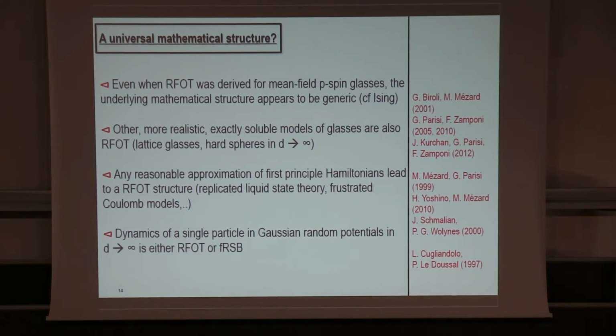But also frustrated Coulomb models. If you try to use approximations to solve it, then you find again this RFOT structure. And even in the simplest case of the dynamics of a single particle in a Gaussian random potential in large dimension, the structure of the problem is either RFOT or one-step RSB or full RSB. And there's a nice paper by Laetitia and Pierre in '97. So again, although the theory seemed to be very narrow in the way it was derived, it seems that it has a very broad degree of generality.